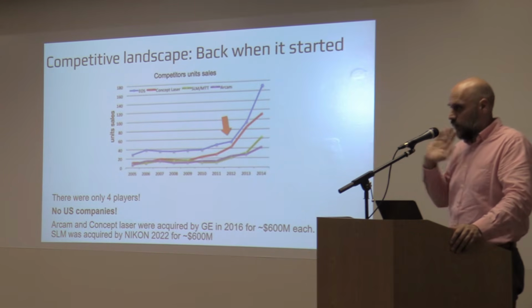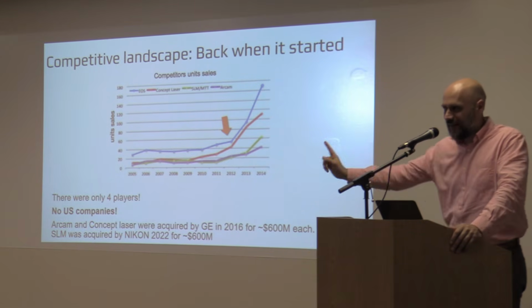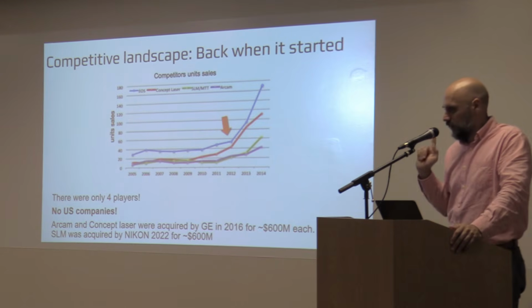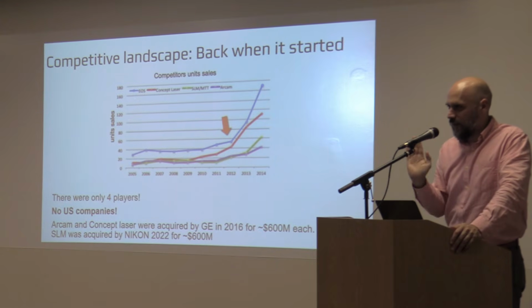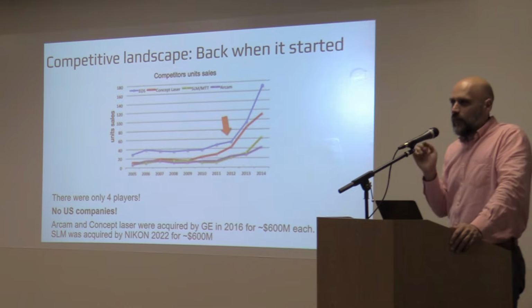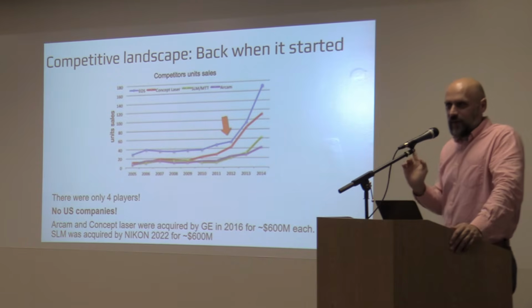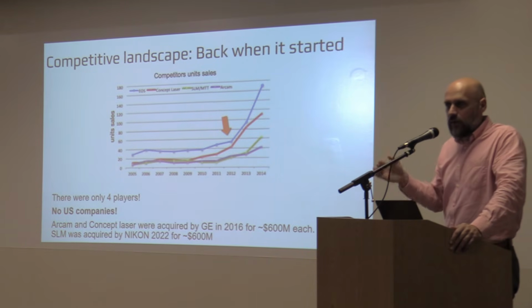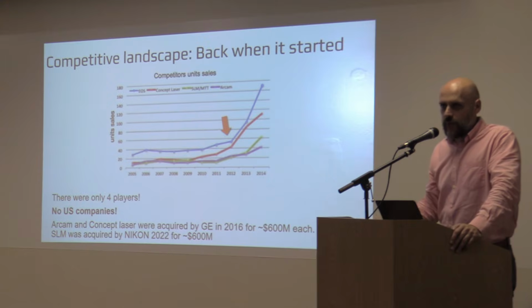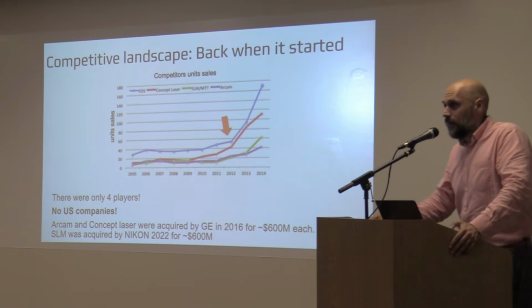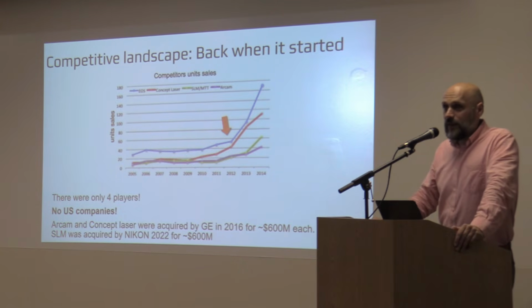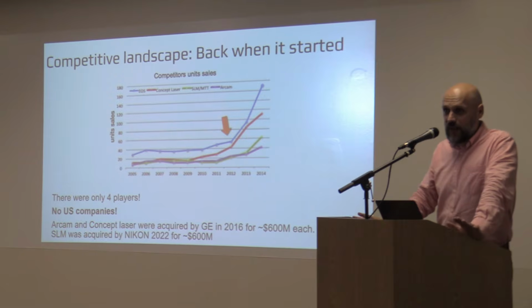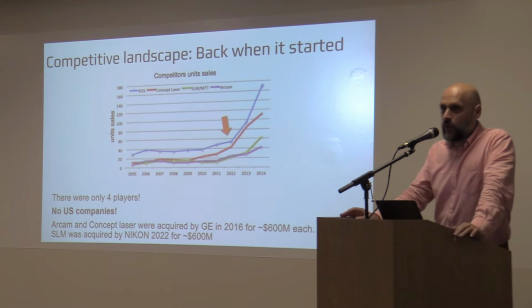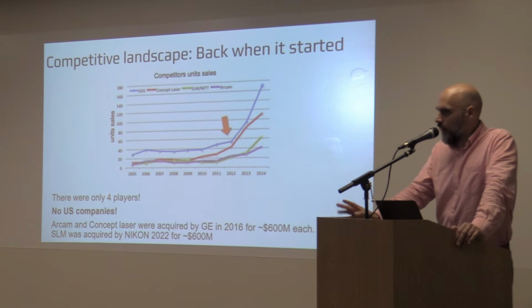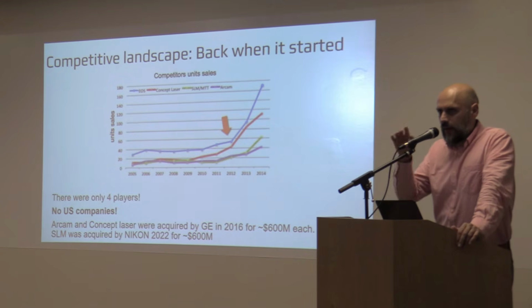Now the toolpath, as it goes back and forth, has a distance between passes, like you move 5 micrometers to the left, another 5 micrometers. If your melt pool is not consistent, you're going to have either over melting or under melting. Both are bad for different reasons, but you have to control that. Melt pool is very dependent on this. The convection patterns in a melt pool are correlated with the oxygen content. I forget the number, if it's like 800 or 2000, but let's say 2000.